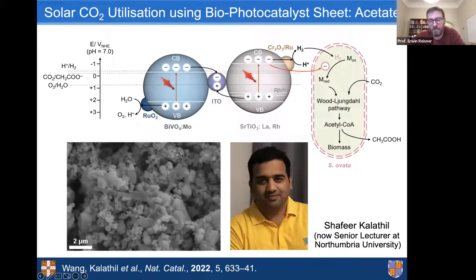And what he did is he replaced now with Qian the cobalt catalyst, and we just started growing bacteria on top of these photocatalyst sheets. And the bacteria we used is Sporomusa ovata, so an acetogenic bacterium that's known to be able to reduce carbon dioxide with hydrogen to acetate. So by growing this bacteria on top, this can actually take up the hydrogen being produced from the ruthenium catalyst and metabolize it with CO2 using this Wood-Ljungdahl pathway to produce acetate.